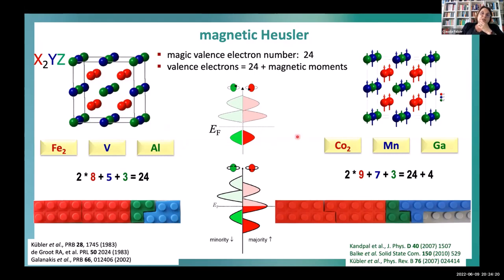But then if you go away from these fully filled states and add additional states, luckily in the case of the Heuslers, it seems they go only in one spin direction. So if we change, for example, cobalt to manganese, I think it's gallium, you now have cobalt with 9 valence electrons, manganese with 7, gallium is 3 and silicon is 4. So you can have then 28 or 29 valence electrons. You put them in one spin direction, and then you end up with an electronic structure like this.